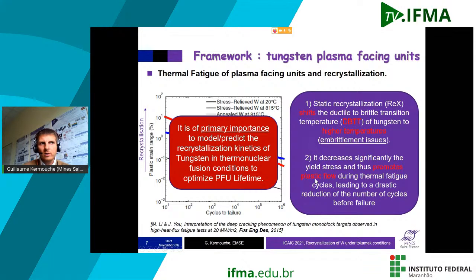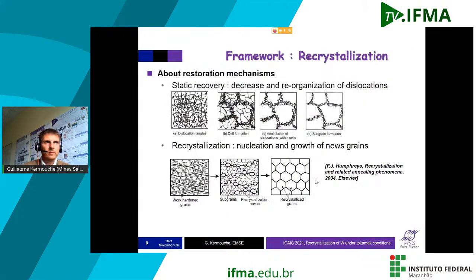So if we want to optimize a PFU lifetime, it is clearly of primary importance to model and predict the recrystallization kinetics of tungsten materials, and that's the aim of this talk. So just a few words about recrystallization. Recrystallization is a metallurgical mechanism that is related to restoration mechanisms. Restoration means that with temperature, with heat treatment, there will be a decrease of the mechanical properties, a softening of the material. So there are two classical restoration mechanisms at play.